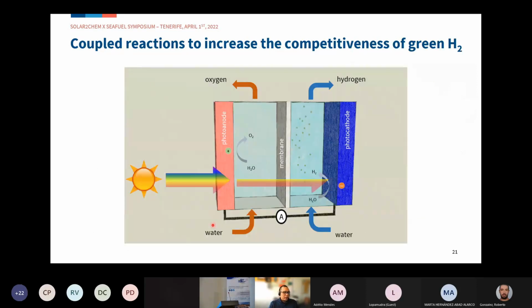One way is to introduce coupled reactions. So if we consider a schematic here where we have a tandem configuration, photoanode and photocathode, at the anode side we produce oxygen, and at the cathode side we produce hydrogen. The green hydrogen we produce here is, of course, what we want, but the oxygen is abundant and low value, about 3 cents per kilogram.